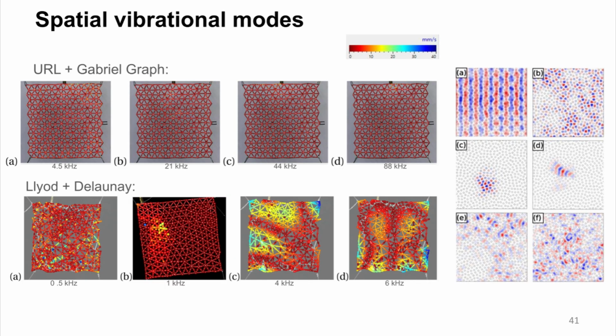I also present some of the preliminary data for metamaterials generated from Lloyd's algorithm and Delaunay triangulation, and compare them with the primary metamaterials used in these experiments, which involve using a point cloud from uniform randomized lattices and connecting using a Gabriel graph. For URL plus Gabriel graph, I did not find any diversity in the spatial distribution of vibrational modes. However, for Lloyd's algorithm and Delaunay triangulation, I did find variations across different frequencies that I measured in these metamaterials, a diversity of spatial vibrational modes.